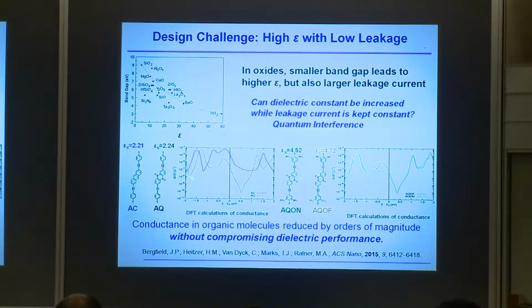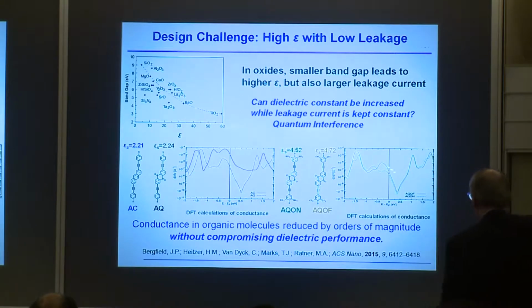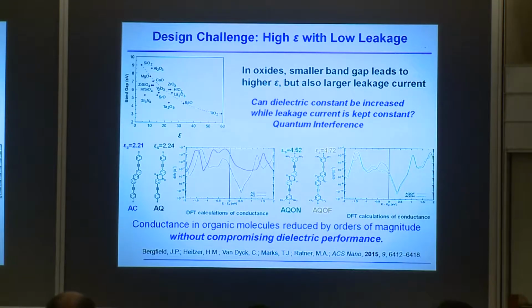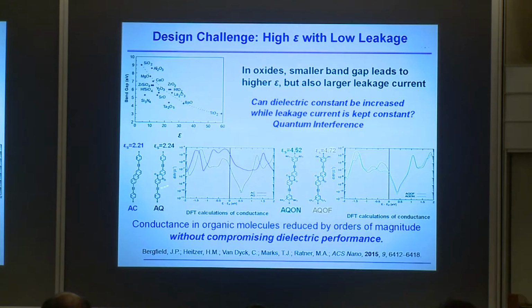Now the problem is, if you were going to make gate dielectrics like this, these are still modest dielectric constants. So what happens if you put donors and acceptors, a classical strategy to increase the dielectric constant? And you can see you can get really quite sizable dielectric constants. We want to go higher, and you still get this point where the conductance falls off. So we think this is really interesting. Now, you might say, well, wait a minute, I've got some inorganics that have high dielectric constants. The trouble with a lot of them is they're semiconductors. They have a high dielectric constant because the band gap is small, and so they're not good at insulation.